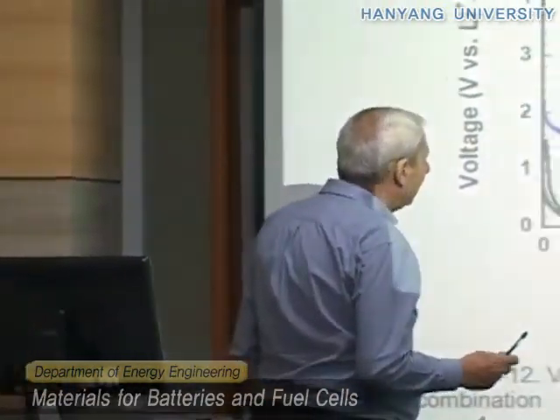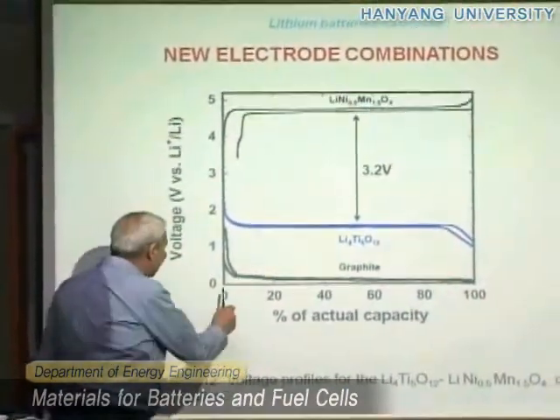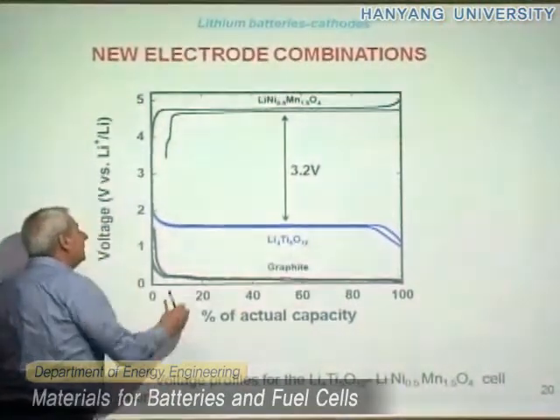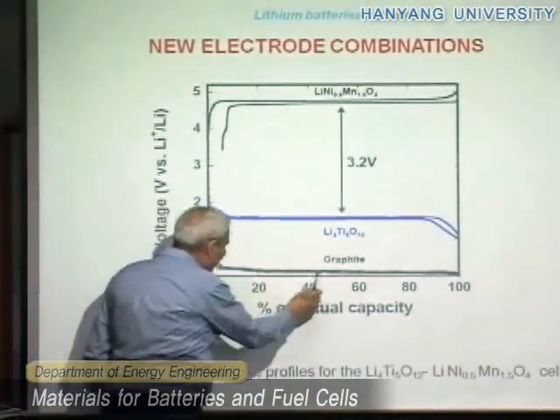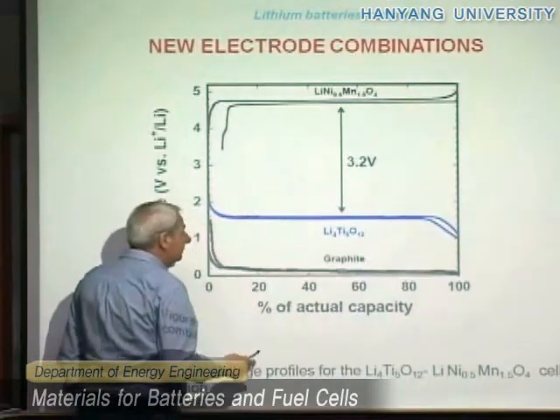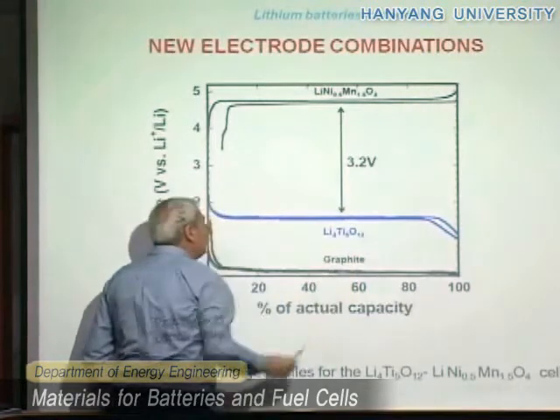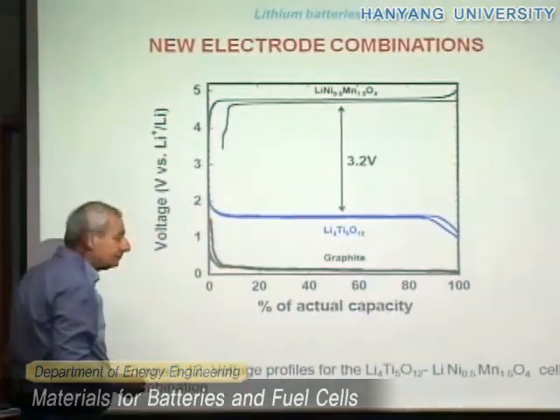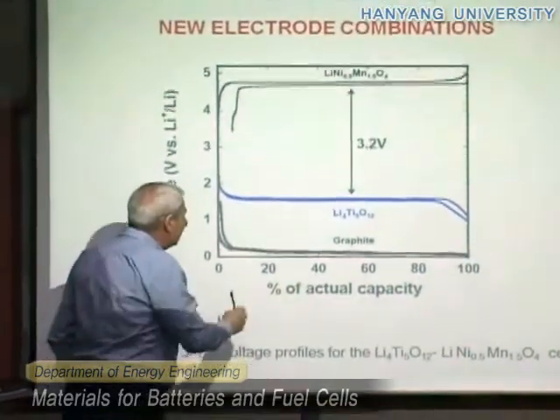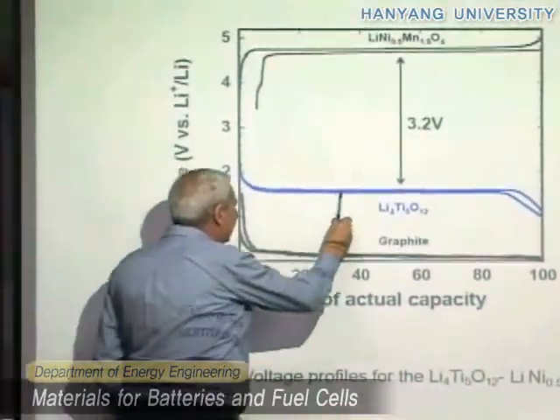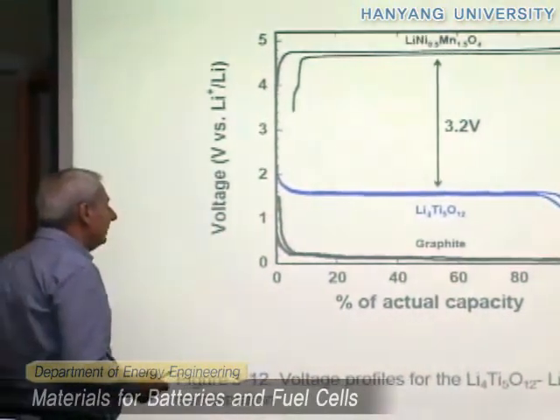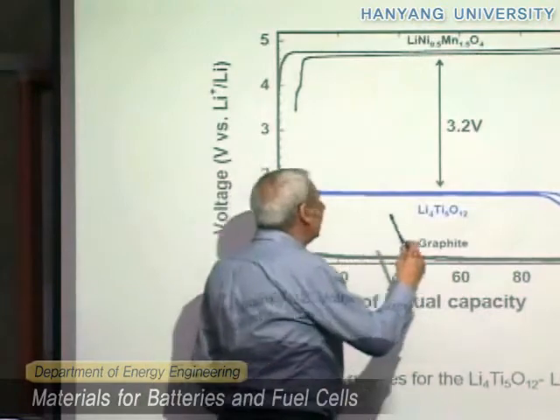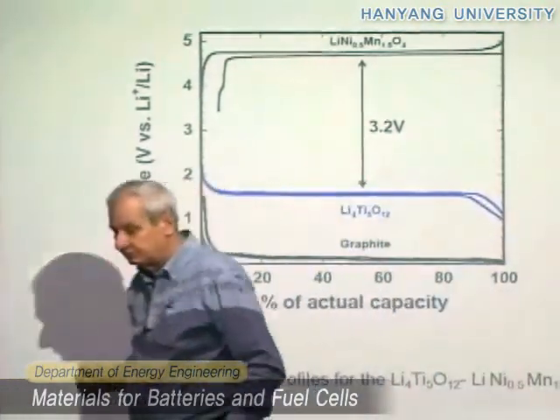The combination of the 4.7 volts of lithium nickel manganese oxide and the 1.5 volts of lithium titanium oxide gives us a 3.2-volt battery — and this was the battery that Dr. Ramin showed us. If you have a battery formed by graphite and lithium nickel manganese oxide, the voltage of the battery is the difference of the voltage of the two materials: graphite operates at about zero versus lithium, so the voltage is about 4.7 volts. When we replace graphite with lithium titanium oxide, which operates around 1.5 volts, the voltage goes down to 3.2 volts — lower voltage, but much higher stability, provided that you have an electrolyte that allows operation at this high voltage.